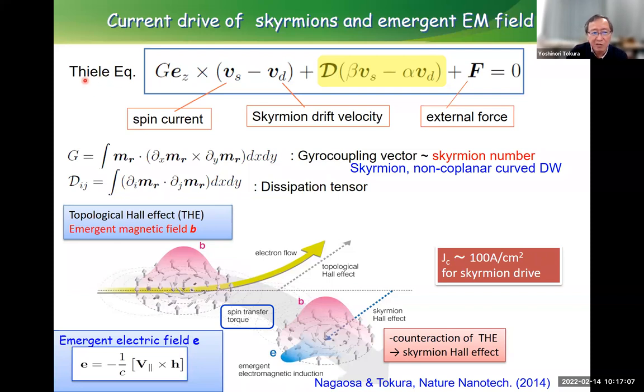equation of motion is described by the so-called Thiele equation. The usual domain wall terms are this kind of damping term, and the dissipation term is important. But in the case of the skyrmion, this kind of term is dominant. This term, Vs, is the spin current velocity, and this is the skyrmion drift, the actual skyrmion velocity. And G is this kind of M dot (dM/dx cross dM/dy). This is nothing but the skyrmion topological number. In general, it's called the gyro coupling vector, and it is the skyrmion number itself in the present case. So where the skyrmion is there, almost Vs equals Vd, and this term is dominant. That is the reason why we observe a very, very small current density to drive the skyrmion in the ideal case.